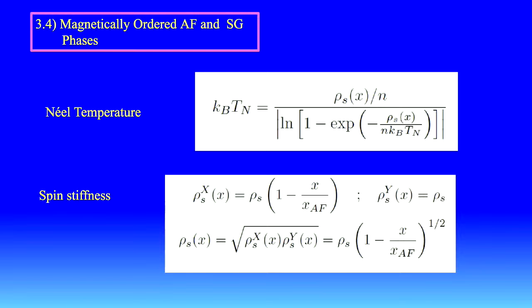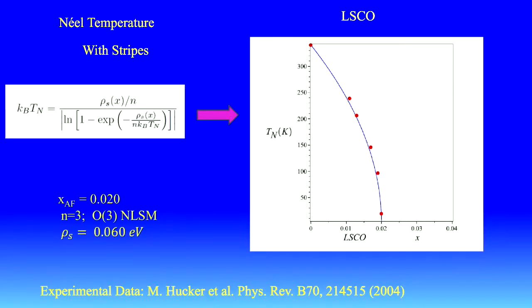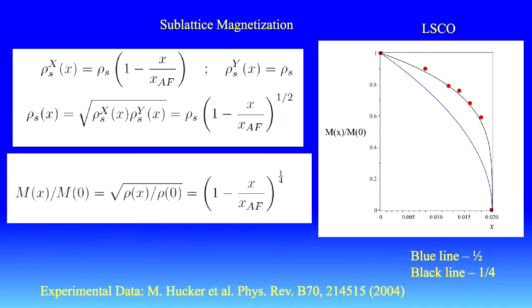Now we go to the magnetic sector, antiferromagnetic and spin glass. So the Néel temperature turns out to be given by this expression, where rho x is given by this. I'll be quick. You see? There's no adjustment of parameters here. The only thing we enter is the value of this, and we enter the value of the spin stiffness. This is the sublattice magnetization, which is the square root.